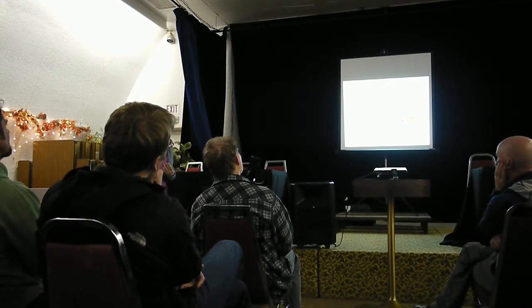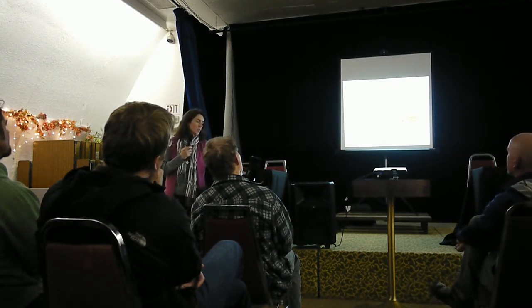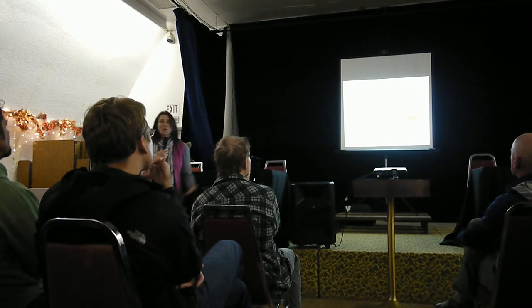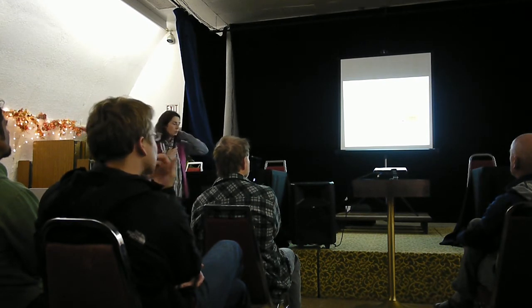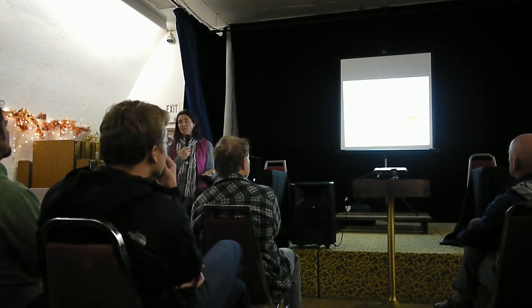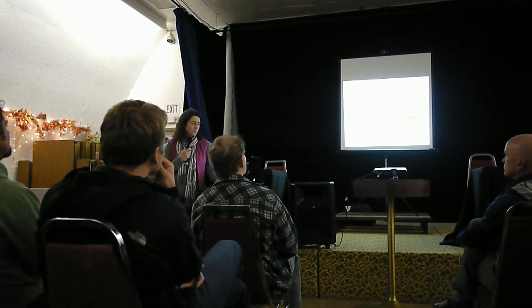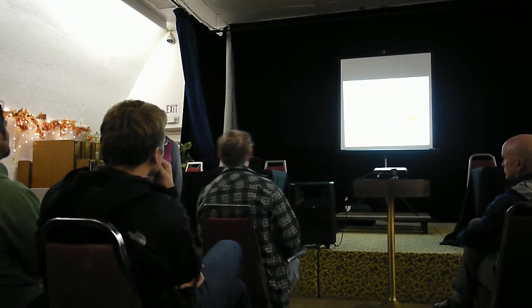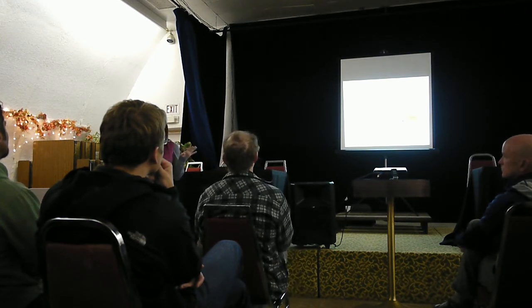But what we quickly saw was that the sodium-calcium and the sodium-magnesium ratios were not the typical signature of sea salt. Sea salt is mostly sodium chloride, and then you have some magnesium and calcium, and you look at the ratios, and you should have like 25:1 sodium to calcium in sea salt. You should have like 8:1 sodium to magnesium ratio. And we were getting like 1:1 and 1 to 6.4. So there's a lot of calcium and a lot of magnesium in this hanger. Who cares? Well, what's the study I showed you that shows that that's kind of important? Yeah, the Japanese study. But we're on a coast, so it should be really high humidity. Shouldn't be a big deal, right?